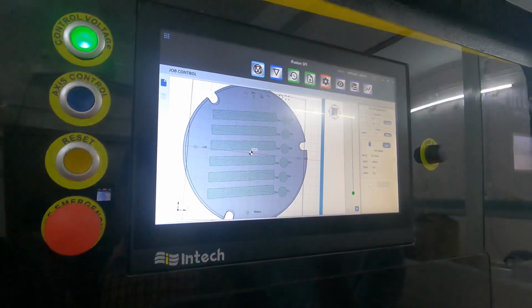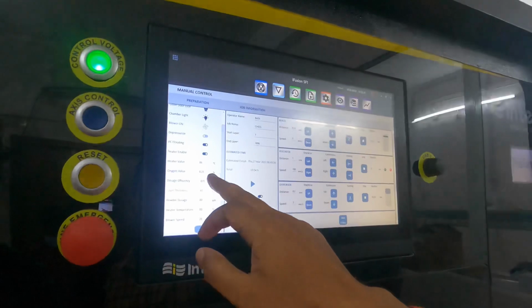So due to this, residual stresses will be generated, and when these stresses are very high, it will get delaminated from the base plate. After that, we can see the oxygen value here. Right now it is 0.35, but you can print the component below 1% of oxygen.